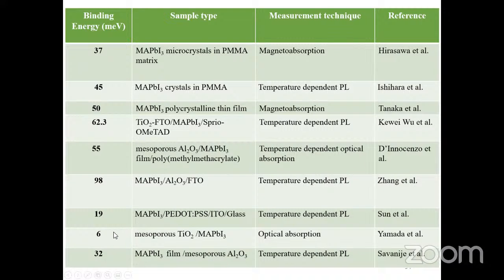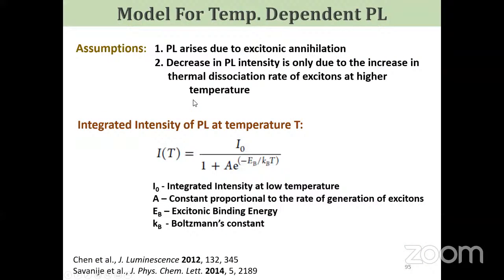You can see reports ranging from 6 millielectronvolts to 98 millielectronvolts, all kinds of values. The way we often measure is to look at the photoluminescence as a function of temperature. If the excitonic binding energy is large compared to the temperature, they bind very well and recombine, giving me photoluminescence. But if the temperature is large, it breaks apart the exciton, so they cannot recombine, and I don't get photoluminescence.